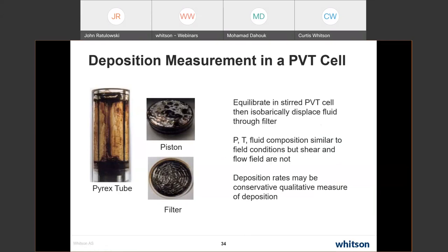So this really doesn't give you much on deposition rate because the fluid mechanics in the cell are much lower shear. Some of this stuff, like on the pistons, particularly the lower piston, is settling. It's not really depositing. But it does give you a little bit of an idea of the tendency of the asphaltene to stick to something. And actually some of the early coating tests, we put coatings on these metal surfaces, the pistons and things in the PVT cell. And we did see differences in the amount of deposit on coated and uncoated systems.